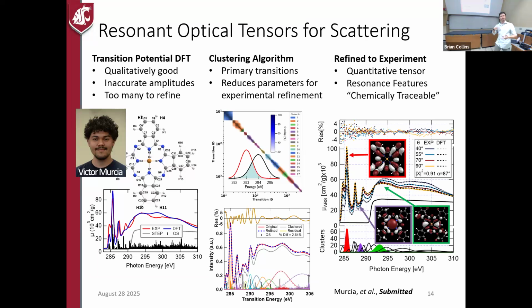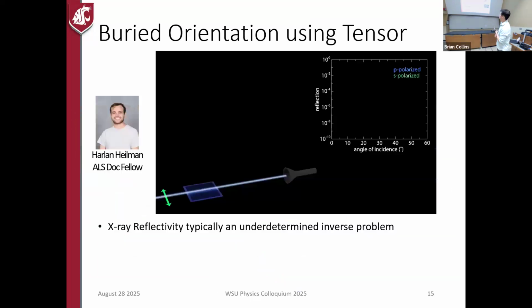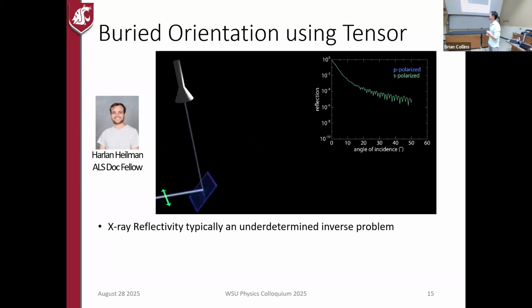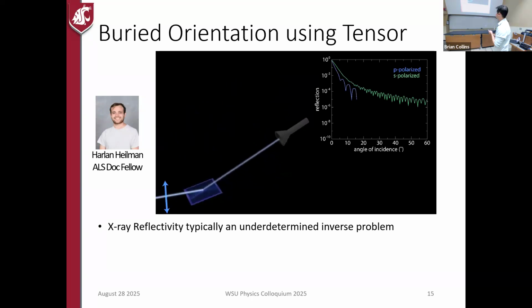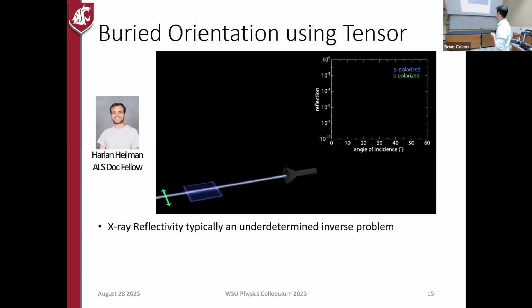But we want to use this. How useful is this type of optical model? That's what Harlan Heilman is doing right now in his PhD research. He's using what's called X-ray reflectivity, and this animation here is from my actual postdoc advisor at NIST. He made this; he's really good at Blender. You're seeing the reflected beam intensity as a function of angle, and you're changing the polarization, and doing that for every different energy across the absorption edge.